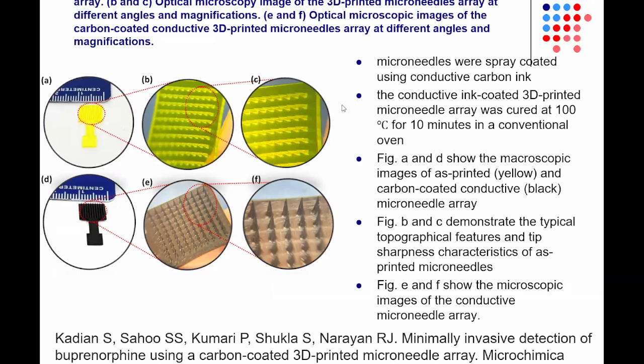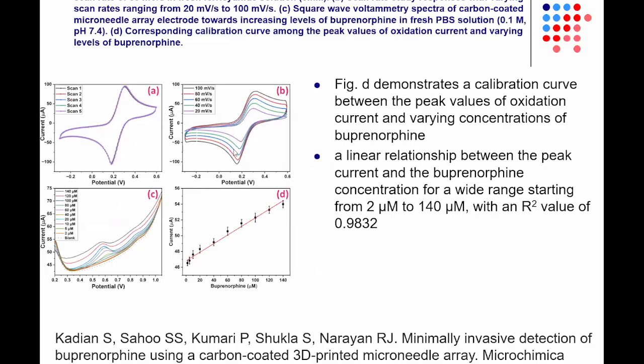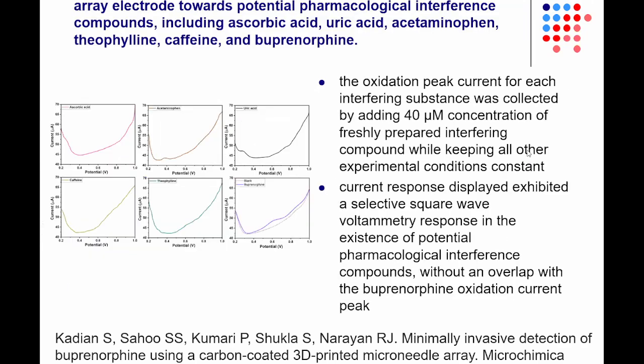Here you can see an example of buprenorphine detection, where we have carbon-coated conductive microneedles that are being used for the detection of buprenorphine, which is used in opioid use disorder as a potential treatment. So you can see here a good linear relationship between the peak current and the buprenorphine concentration, for 2 micromolar to 140 micromolar values. You can see here that you don't have overlap of the buprenorphine curve with the curves of the potential interferences like ascorbic acid, acetaminophen, uric acid, caffeine, or theophylline.